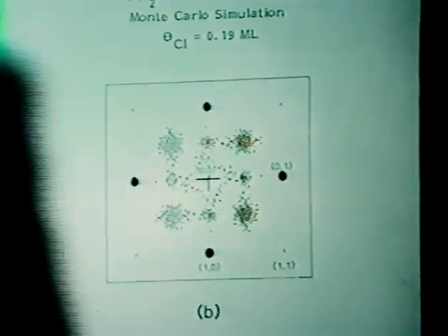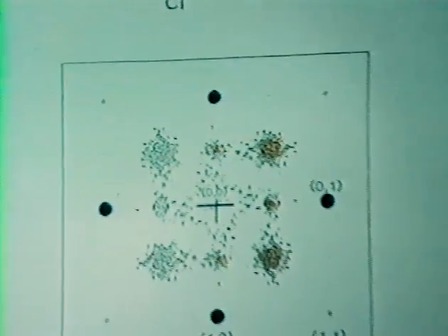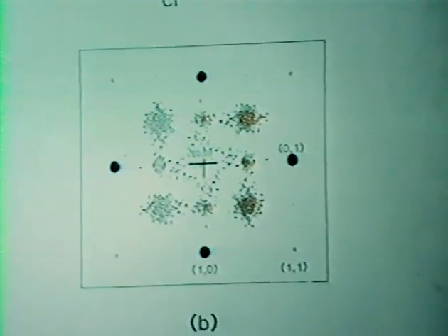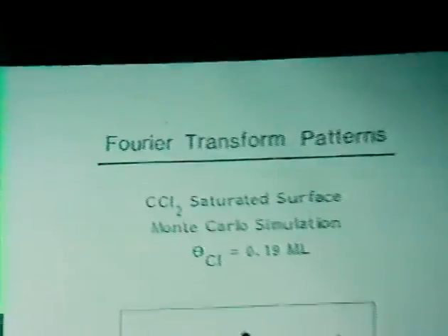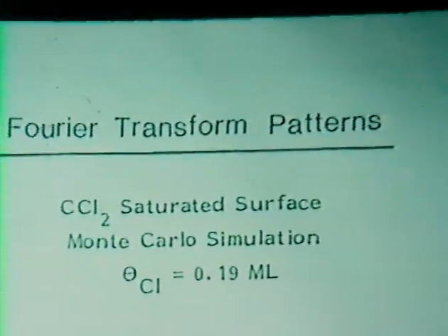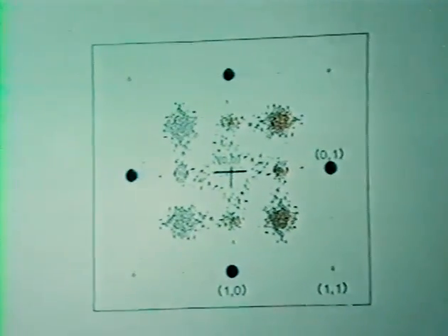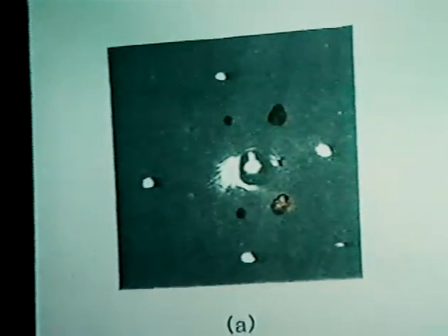Now, if you engage in simplistic thinking like this, incidentally, these are the fuzzy spots observed by LEED and produced by simulation of these structures. And this is why we know that these structures really exist, because we investigated 17, 18, 19 different structures, and only those which give us the fuzzy spots in the right positions are then the accepted structure. So basically what we do here is a simulation of partially disordered ensemblic structures.